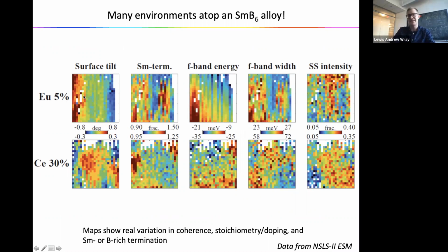But what we found when we took these strongly correlated topological insulator alloys and applied the same technique to them very recently, is that there's potentially a lot more richness to what you can find. You can look at the width of the F electron states, which tells you how coherent the states are. When the F electron states are broader, it means that you're starting to depart from the quasi-particle picture that gives rise to band topology. And when we dope the material heavily with a magnetic element like cerium, we can suppress this coherence almost to the point, in this case, where we're losing the surface state. So we can play with that physics as a departure from the topological regime.